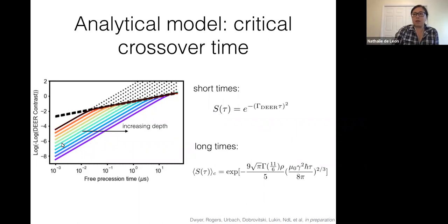Somewhat surprisingly, if you then calculate the results from this analytical model, what we see is not a single exponential that gives you something in between these two exponents, but instead a crossover time. So at early times, this is now on a log plot, which is not that easy to understand, but it gives you the very nice visual feature that the slope corresponds to this exponent. So what we see is this transition between a slope of n equals 2 and a slope of n equals 2/3, and there's a sharp kink in between. And this crossover time is directly related to the depth of the NV center. As we increase the depth, this crossover time gets pushed further and further out.